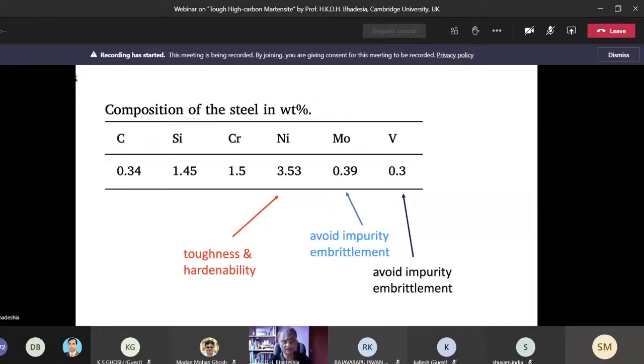So here is the steel design that we came up with, and to cut a long story short, we have a carbon concentration of the order of 0.4 weight%. We need to add molybdenum because in a commercially produced alloy, we will have impurities which tend to segregate to the austenite grain boundaries if we don't have the molybdenum. The vanadium is there as a microalloying element in order to control the austenite grain size during the hot rolling process. And we've got a certain amount of nickel to enhance the toughness and the hardenability, chromium as well, because we want the martensite to be generated immediately after hot rolling.